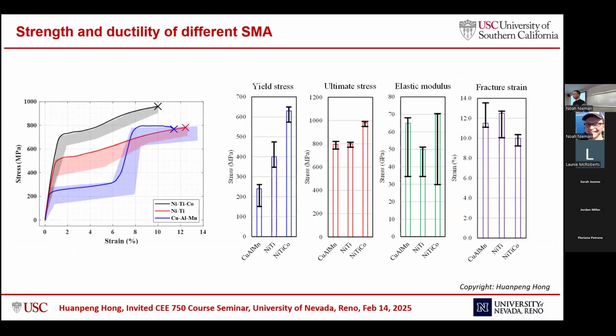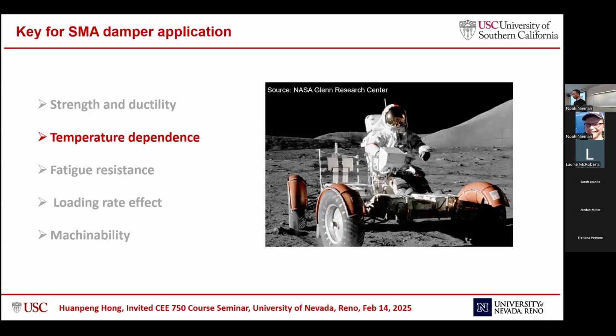First, here's a comparison of the nickel titanium cobalt, nickel titanium, and copper aluminum manganese alloy. This is the monotonic stress strain curve. We see that the copper aluminum manganese alloy is around 250 megapascal, nickel titanium around 450 to 500 megapascal. This is comparable to conventional steel. And for the nickel titanium cobalt, it can be as high as 650 megapascal. So time is limited. I'll speak a little bit faster because I have so many things to present.